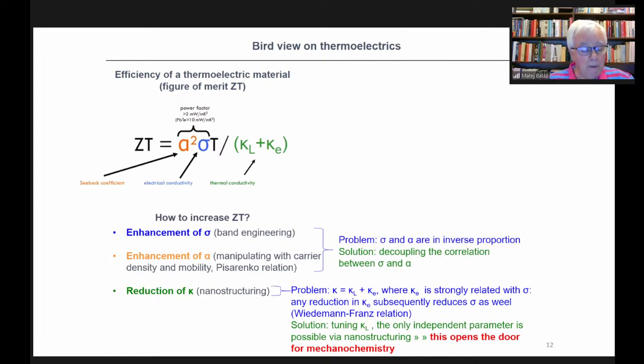And then we have another problem. This is the so-called Pisarenko relation or Pisarenko limit, which concerns the simultaneous enlargement of Seebeck coefficient and electrical conductivity. The problem is that these parameters are not separate and interact with each other. However, we have one good thing: thermal conductivity is composed of two terms, electronic thermal conductivity and lattice thermal conductivity, kappa E and kappa L.